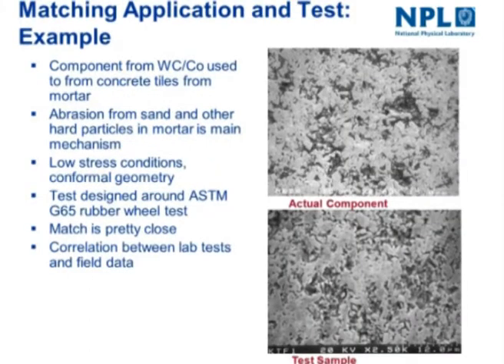An example of matching the application to the test is given here, and this is a firm that was producing concrete tiles for roofs, and they used a tungsten carbide cobalt component called a slipper blade to actually form these tiles. And the big problem they had was that they got a lot of abrasion from sand and other hard particles in the mortar mix that wore the component, and they wanted to improve the component lifetime. So we did a program of testing.